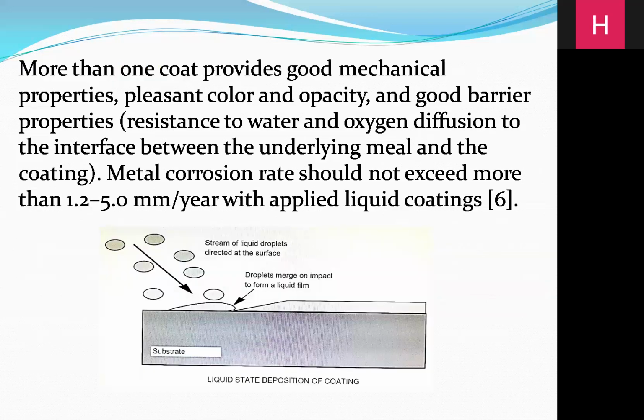Okay, coming to the next slide. More than one coat provides good mechanical properties. If you use only a single coat, it has only some properties and is good for only a few days or few months. But if you use more than one coating, it provides good mechanical properties to the metal, pleasant color and opacity, good barrier properties, and resistance to water and oxygen diffusion into the interface between the underlying metal and the coating. Metal corrosion rate should not exceed 1.2 to 5 mm per year with applied liquid coatings.